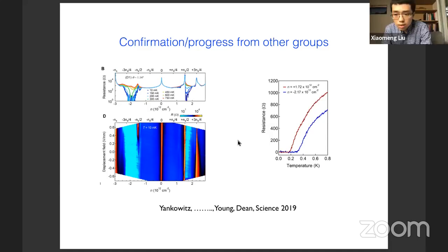Okay. Question from Kasra: with the HBN substrate not aligned with the twisted bilayer graphene sample, is the C2T symmetry at a microscopic level preserved? Would it impose the gapping out of Dirac points? Okay, that's a wonderful question. Empirically, it does seem to be the case that in the vast majority of twisted bilayer graphene devices at low twist angle that have been studied, for samples that are not aligned with HBN, C2T is preserved and neutrality is Dirac-like.